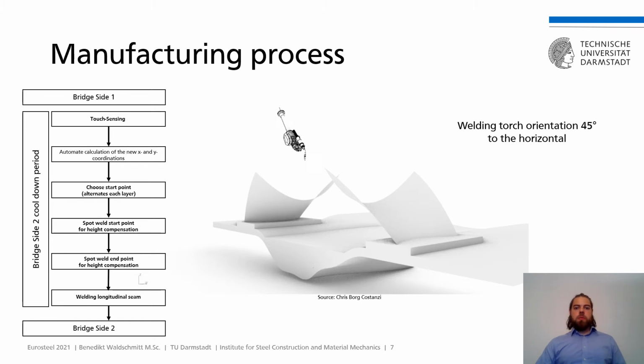Next, we turn to the welding process itself, shown on this animation. The start and end point of a weld seam are flatter than the continuously welded area. For the bridge, there is also the special case that the geometry not only protrudes in the longitudinal direction, but also expands in the transverse one. Therefore, additional material must be applied at these points by a supplementary process step.